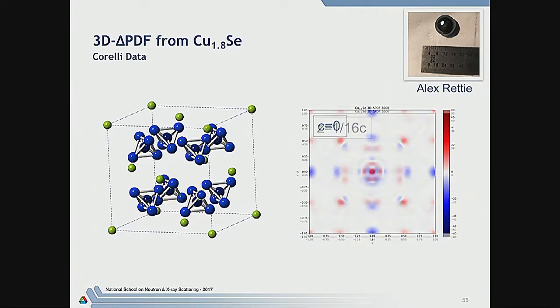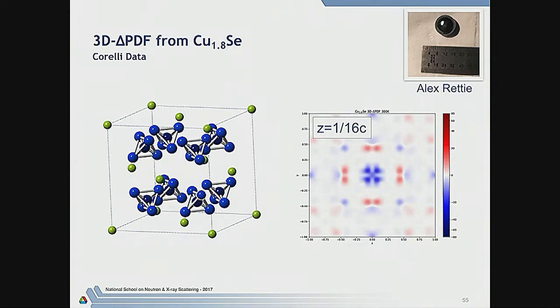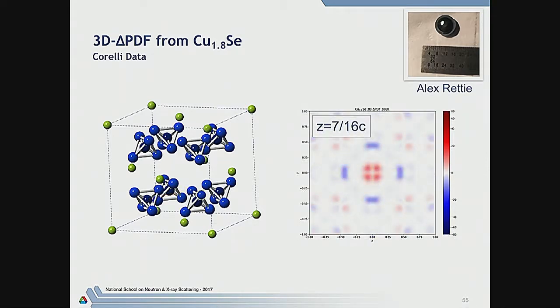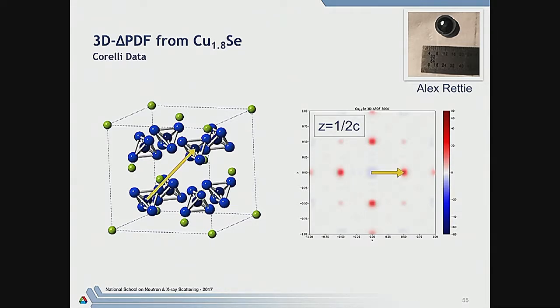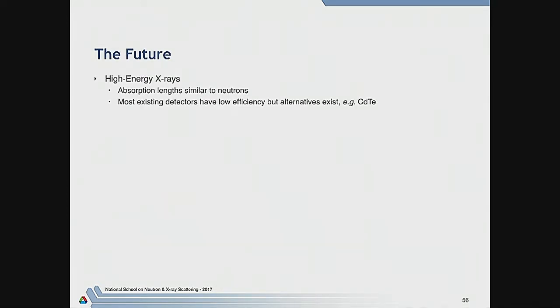But if you go up a little bit in z to a sixteenth, you're now probing these kinds of vectors, and you can see that these are red. So for some reason or other, neighboring tetrahedral sites will be occupied if these ones are not. And you can go through the whole unit cell. So this 3D PDF technique, again, gives you model-independent insights into the nature of the disorder without having done any kind of complex modeling. So, I'm sorry, I should have left more time for questions. So this is anyway the final stages.